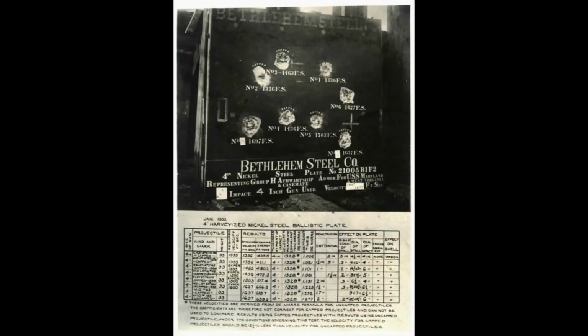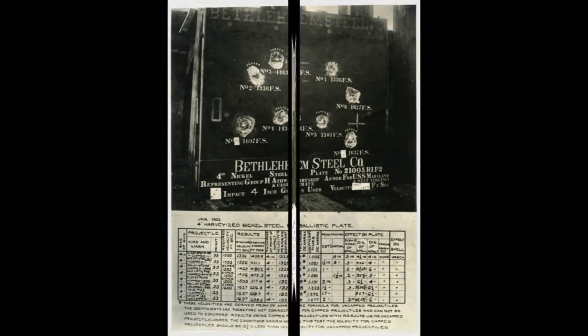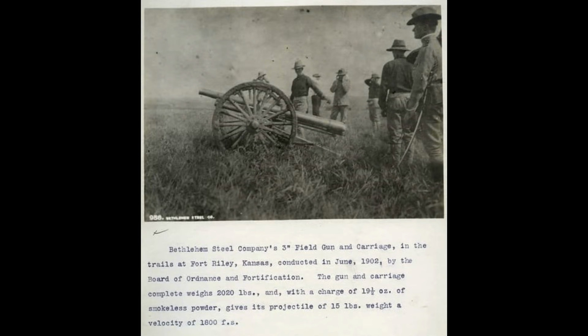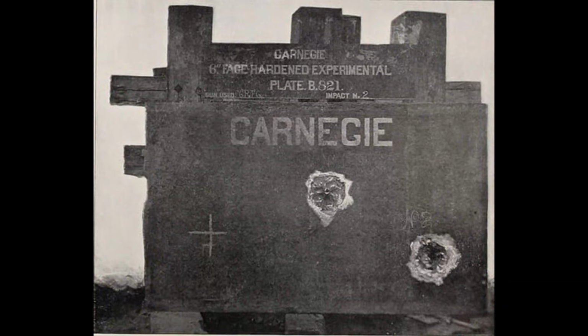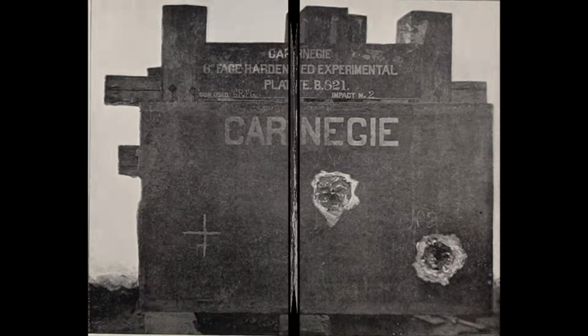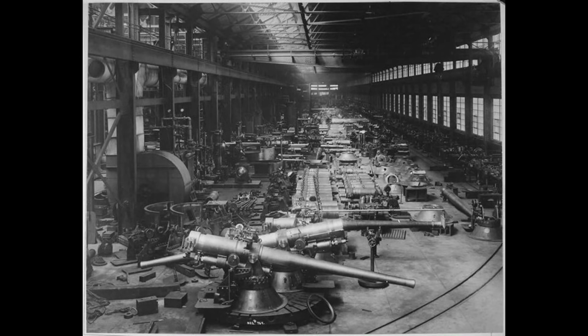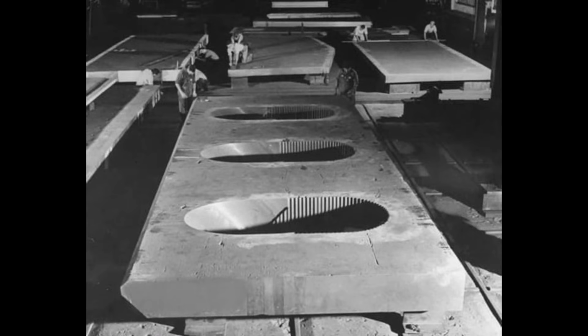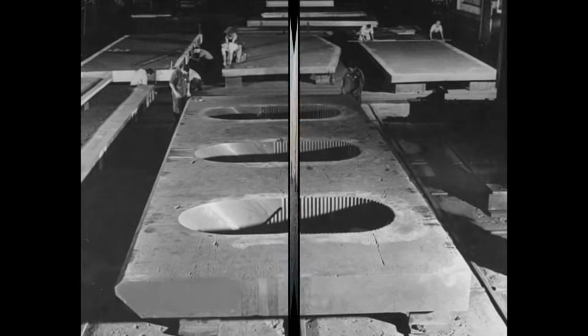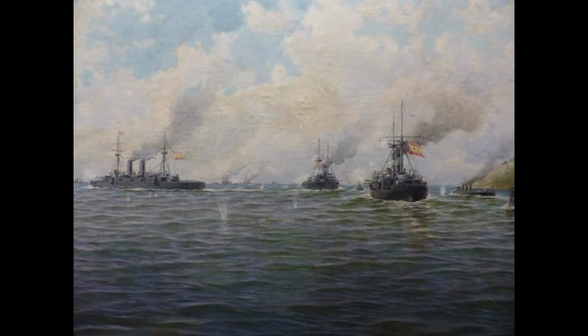"We are building ships that will sink in the first engagement," he tells Congress in 1890. "We need better armor, or we need to stop building battleships." The steel industry offers no solutions. Carnegie Steel Company's metallurgists experiment with nickel-steel alloys. Better than iron, yes, but not good enough. Plates still crack. Tests at Bethlehem Steel show 35% failure rates.